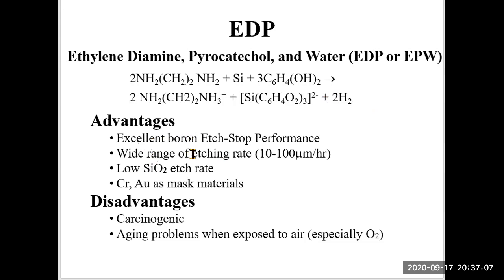Advantages of EDP: excellent boron etch stop performance. Later we will explain what a boron etch stop is. EDP also has a wide range of etching rates, from 10 to 100 microns per hour, and a low silicon dioxide etch rate, so silicon dioxide can be used as an etching mask. Chrome gold can also be used as a masking material.